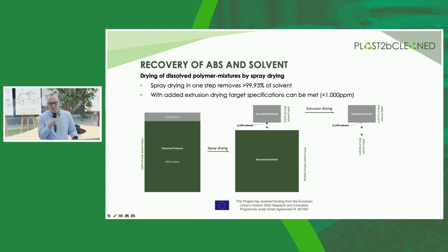with spray drying, starting with a roughly 10% cleaned polymer solution, we sprayed that and removed over 99.9% of the solvent in one step. And if we later add some additional extrusion, we reach our target of below 1000 ppm, which is sort of a processing target. Below 0.1% of residual solvent is very important for further processing. What is to mention here is also that those numbers are actually outdated. In the last campaigns that we ran, we actually managed to even go below the 0.1% with just the spray drying. So I think here we're on a good track, and obviously we want to further pursue that.